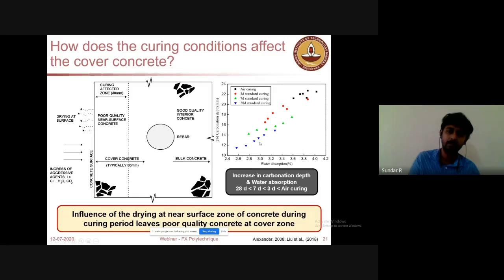And if the curing is extended to 28 days, you could see the water absorption is also reducing. So water is one of the sources for corrosion, and CO2 is another. When you have sufficient curing, you are able to reduce the risk of carbonation induced corrosion, as well as other forms of deterioration mechanisms, because water absorption is a primary source of sulfate and chloride salts also. So when you cure for sufficient time, you get the necessary good quality cover at the surface. That will reduce the problems with respect to durability.